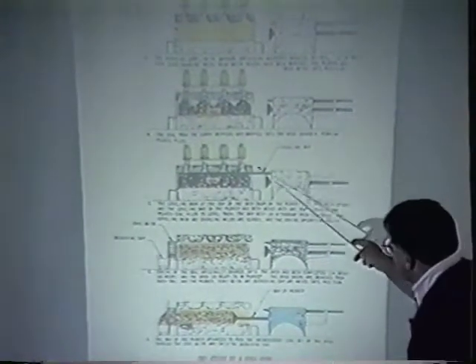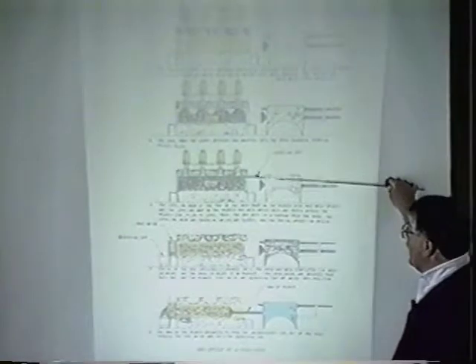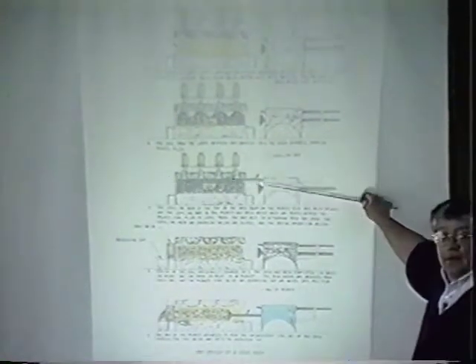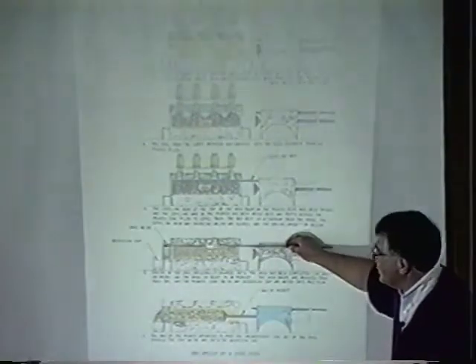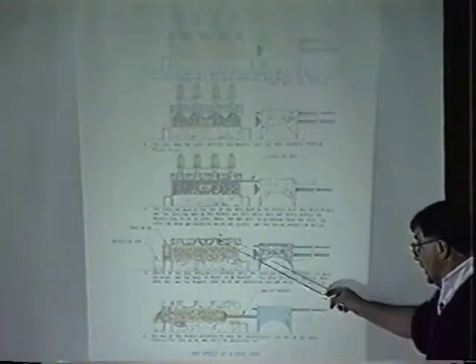Then on this pusher machine, there's a bar, and that bar just goes right across and levels the top of the peaks. Okay, we call it leveling. So, as you can see what it does, though, it gives us a nice little opening for those volatile gases that are coming off during the coking cycle. We can collect them. If we don't, it causes pressure in the oven, and then we can have more emissions. So we do that. Then the coal sits in there for 18 hours.